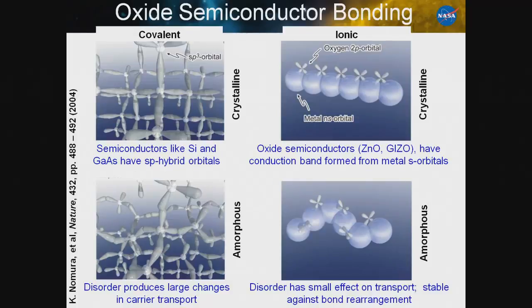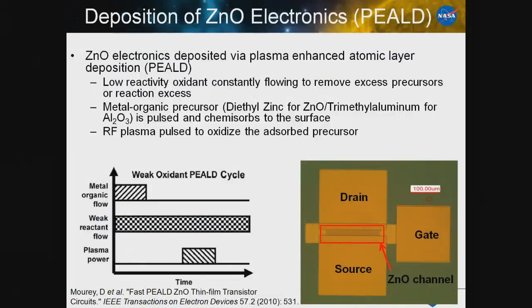In contrast, in oxide-based semiconductors such as zinc oxide, the conduction band is associated with the s orbital of the zinc, which is a spherical orbital. It's much less susceptible to degradation associated with the exact atomic arrangement, and as a result, it's much easier at low temperatures to achieve mobilities of around 20 centimeters squared per volt second.